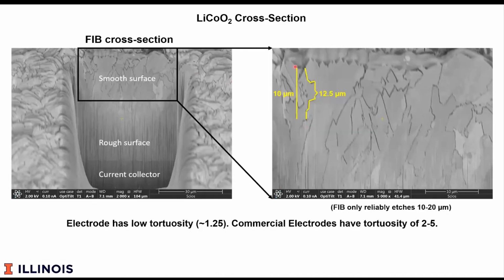And more importantly, if we look at the cross-section, here's a 10 micron distance. We've taken a number of measurements, but I've just highlighted one here. And so the tortuosity of this electrode is about 1.25, even though it is about 90% or so volume fraction. So that tortuosity could not be achieved in a slurry.